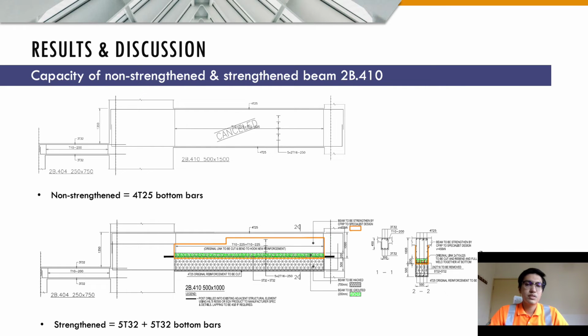So this is the detail of the beam 2B.410. Figure at the top shows the detail of beam before the modification work, which I labeled as the non-strengthened beam. And figure at the bottom shows the detail of the beam that we received from the consultant for the modification work, which I labeled as the strengthened beam. As it can be seen, the non-strengthened beam has 4T25 of bottom bars, while the strengthened beam has double layer of 5T32 of bottom bars. The shaded area is the depth of the beam that is to be reduced. The dark lines on the beam ends show the post-install rebar.